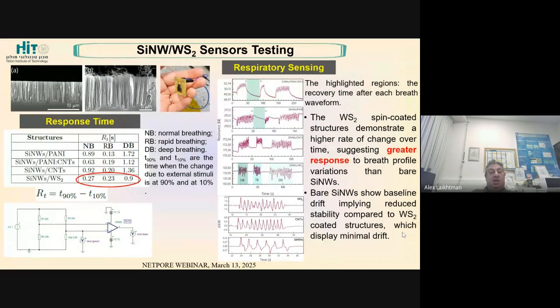Just to show you some more recent results performed mostly in Reykjavik. Here you can see these nanotubes. They are grown with the help of silver nanoparticles. These are not coated nanotubes. These are silicon nanowires coated with either carbon nanotubes or WS2 nanotubes. All measurements are performed based on their resistivity change. Here is the electrical setup for the measurements. It was performed for normal breathing, for rapid breathing, and for deep breathing according to the standards.